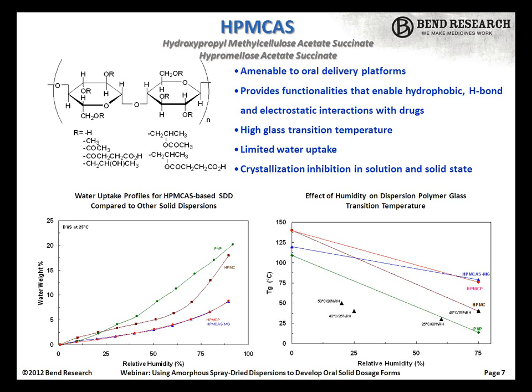HPMCAS has a variety of key attributes that make it a very nice polymer to use for amorphous spray-dried dispersions. One of the key things is that it's amenable to oral delivery platforms. Because of the chemistry of the polymer, it also allows functional enhancement of the supersaturation of the amorphous free drug. The high glass transition allows for stability of the amorphous state in the solid state.